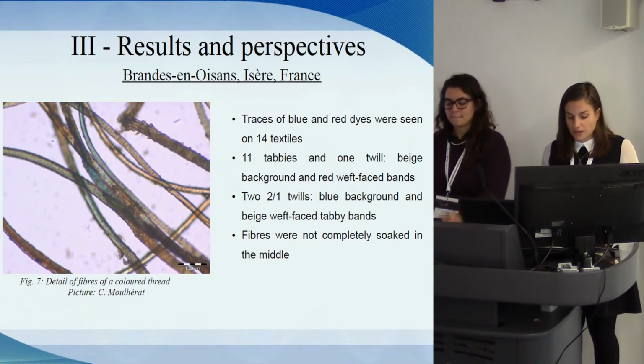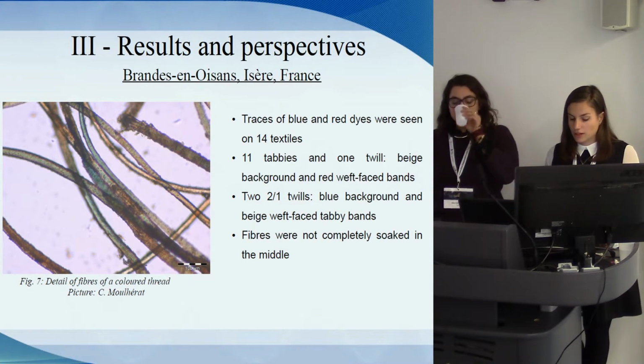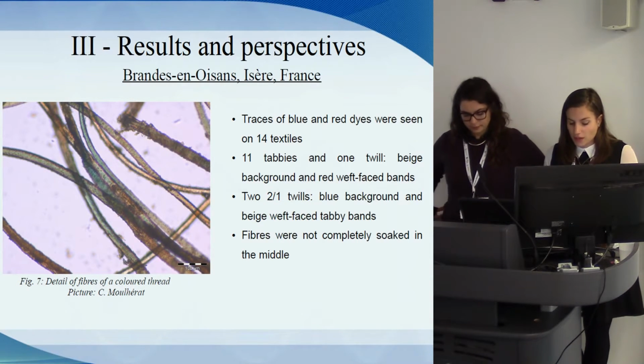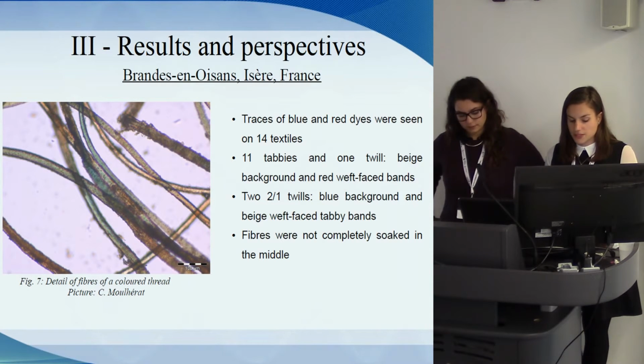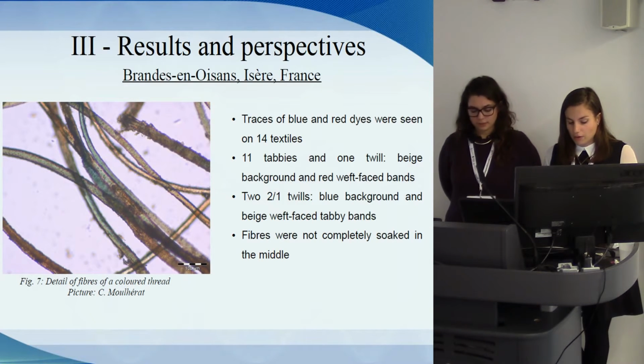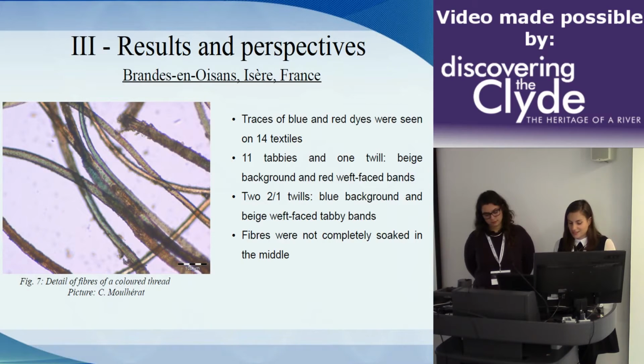Other analyses were made with the help of Christophe Moulhérat at the Quai Branly Museum in Paris. No pigment analysis was realized. Nevertheless, traces of blue and red dyes were seen on 14 textiles. 11 tabbies and one twill had a beige background and red weft-faced bands. Two twills had a blue background and a beige weft-faced tabby bands. Fibers from colored threads were observed under a microscope. This observation showed that fibers were not completely soaked in the middle.